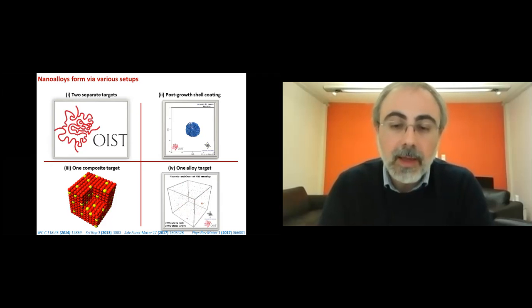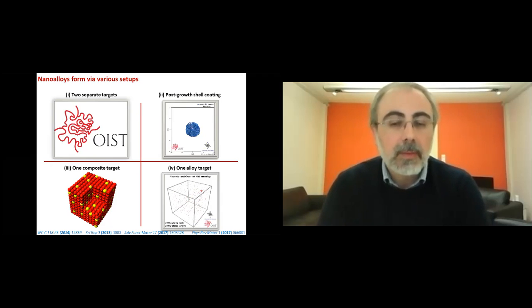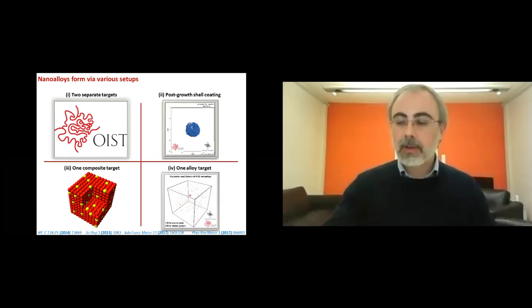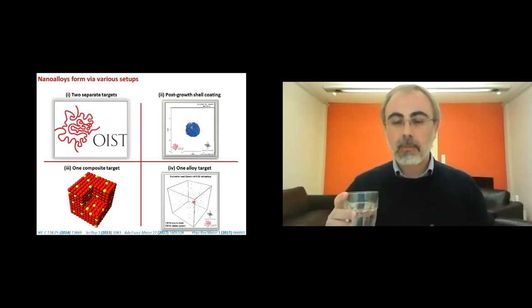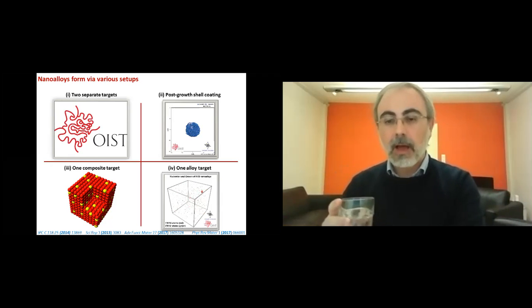So you start very early on by having mixed nanoparticles. And this corresponds very well to the experimental setup where atoms sputtered from an alloy target are already in the same thermal environment and they nucleate together, creating mixed nanoparticles. Of course, then the two phases may segregate post-growth.